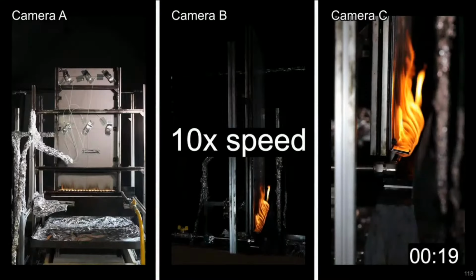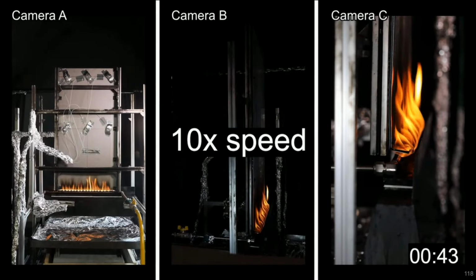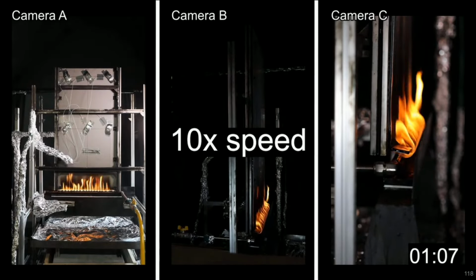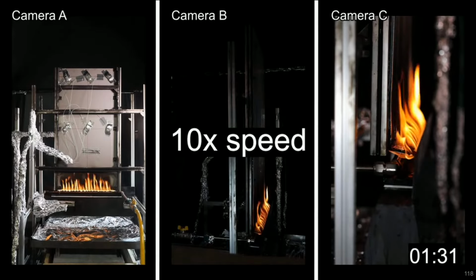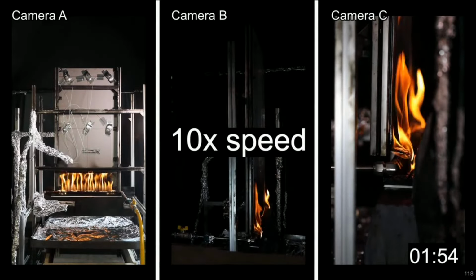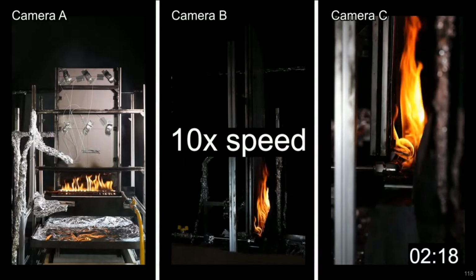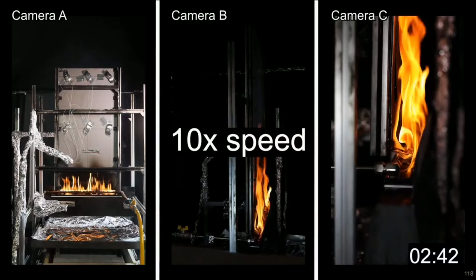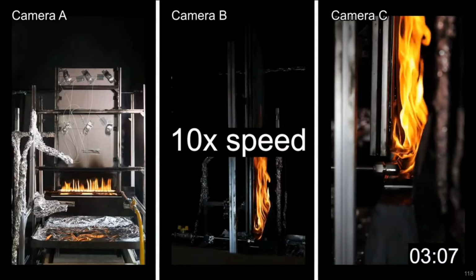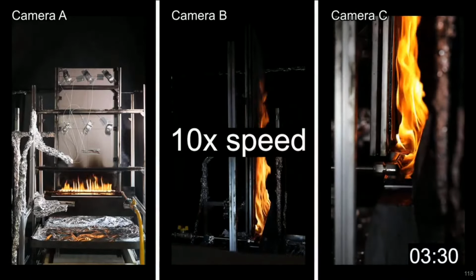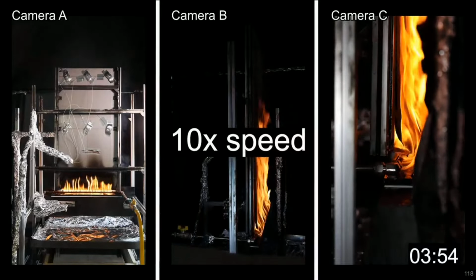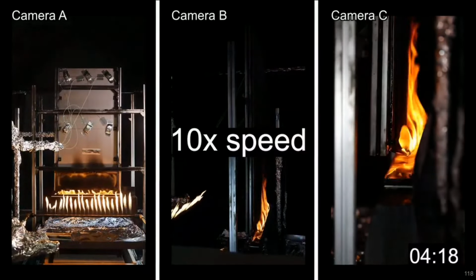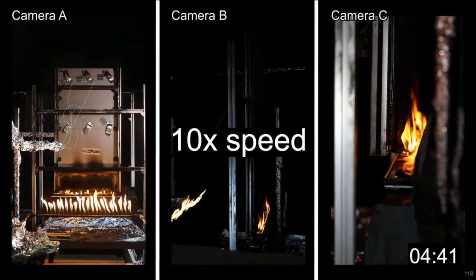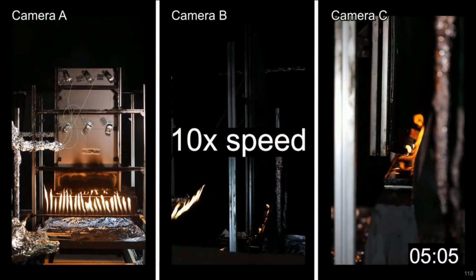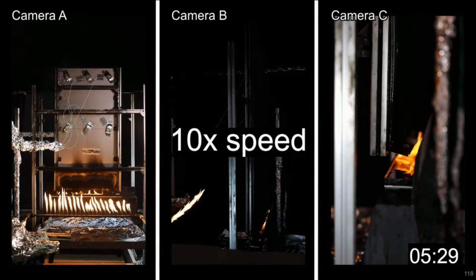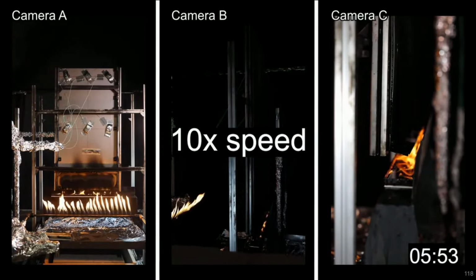And I'm just going to show this for you in the interest of time at 10 times speed. So you can see the burner gets inserted. After about 1.5 minutes, you see dripping. We see the aluminium plate fall off of the little shelf on the ACM PE. We will see the line burner removed at 4 minutes. And we will see that eventually this experiment goes out. So we do not observe escalation to full involvement of the ACM in this case.